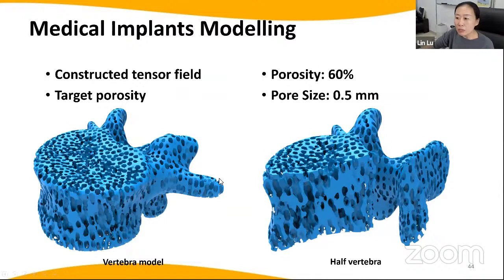Also, we consider how to model real bones as the porous structure. Here I mention that for the implant, it does not need to be biomimetic. As we can see, there are many regular implants that have already been used in mechanical applications. So here we consulted with doctors, and it did not need to be organic. This is just an example to show the modeling result. For this kind of vertebra model, the porosity is usually 60%, and we have the pore size as 0.5 millimeter, and we get this result.